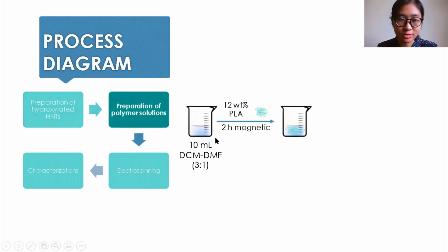So pure PLA solution was carried out by dissolving PLA resins with a 12 weight % concentration in 3:1 DCM-DMF mixed solvent system for about 2 hours at room temperature and then electrospun.